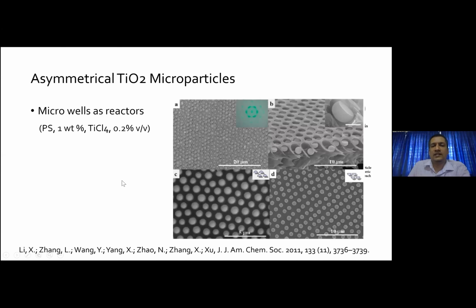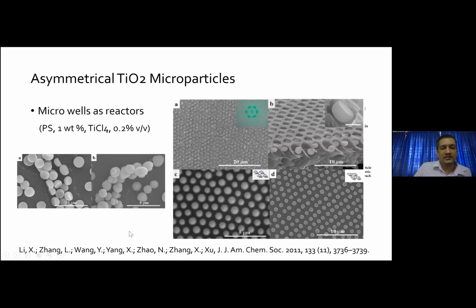They have shown the as-prepared film taken from the vertical, perpendicular angle, and now this is the side view of these titanium dioxide hemispherical microparticles. These particles are peeled off with scotch tape, and you can see the hemispherical region here and the disc region here. So they have proved that it is possible to generate unsymmetrical microparticles onto the surface in a very simple approach. And this is an image of the collected particles.